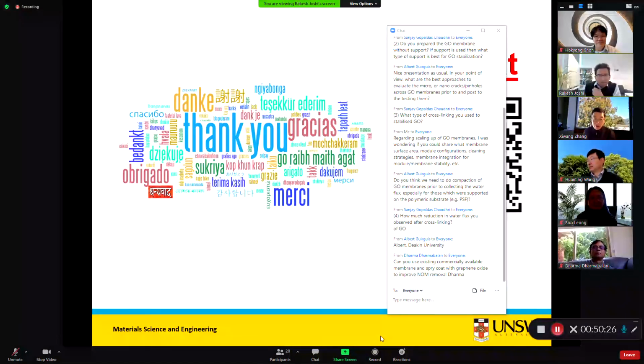Rakesh, the next question is still from Albert. Do you think we need to do a compaction of GO membranes prior to collecting the water flux, especially for those which are supported by polymeric supports? We always test these membranes before, but we cannot test all the membranes. Like one batch, we test the GO membranes for any mechanical cracks. We tested one batch, not all the membranes.